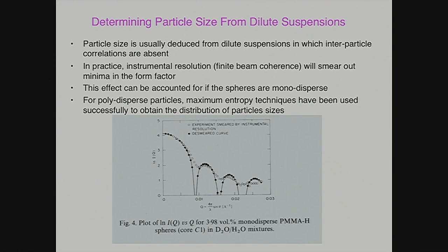Why do you measure the circular dots and not the solid dots? Resolution, yes. So if you want the definition of a radius of gyration of a particle, find the center of mass, and then take elements in the particle, and multiply the mass of the element by the square of the distance away from the center of mass, integrate that over the particle, and divide by the total mass of the object, and that gives you a weighted average of the squared distance, which is called the radius of gyration.